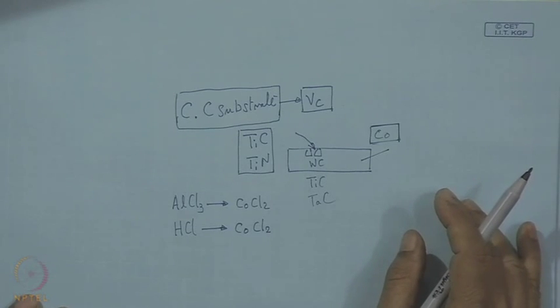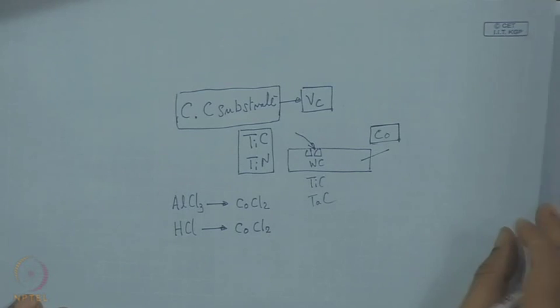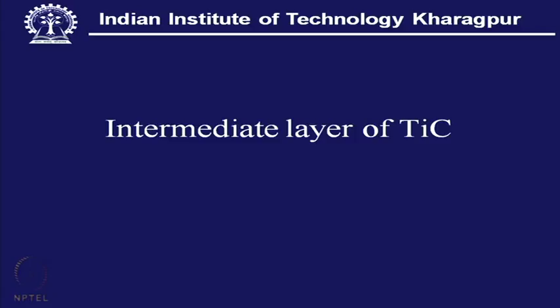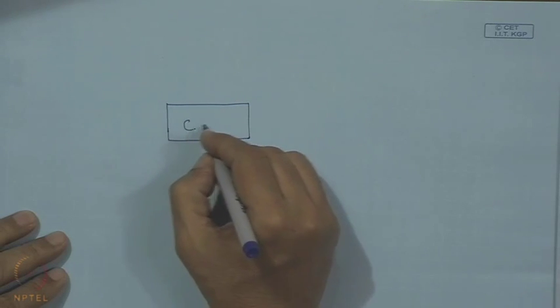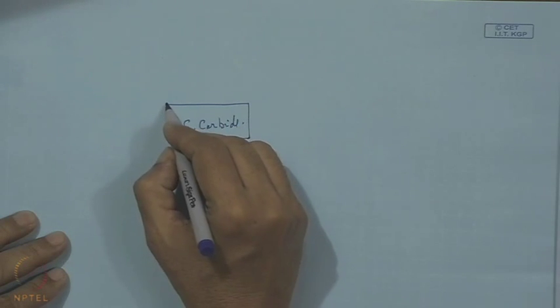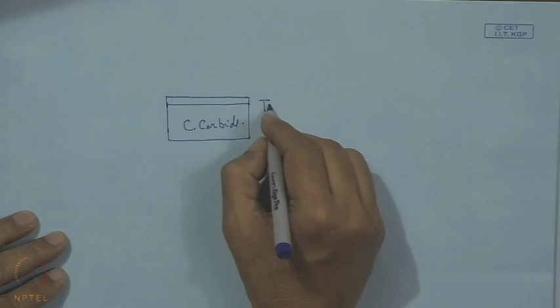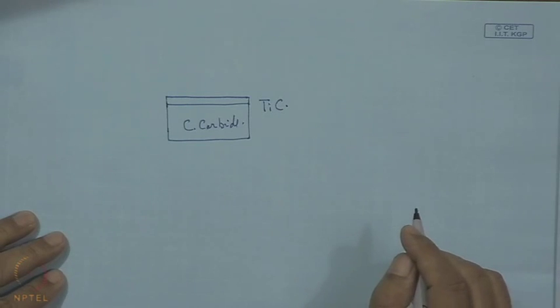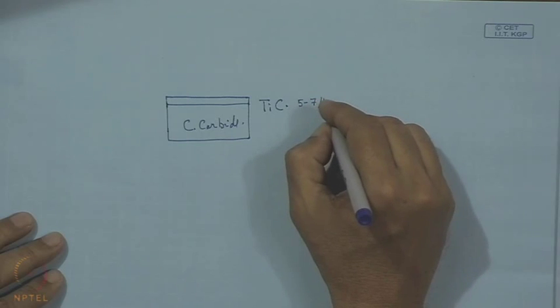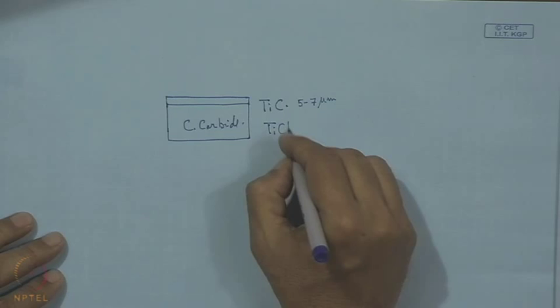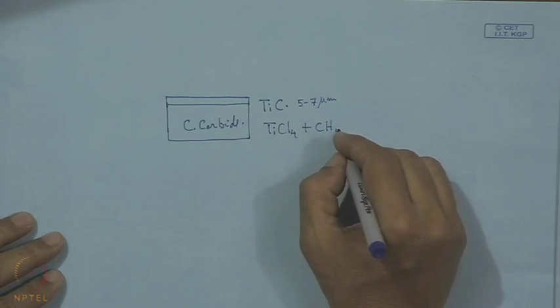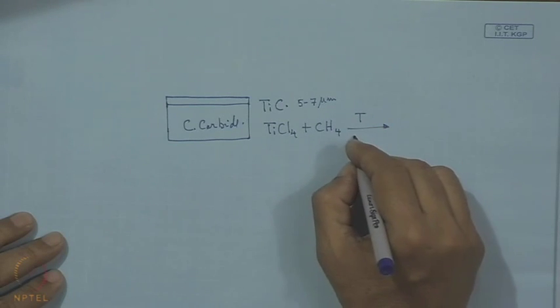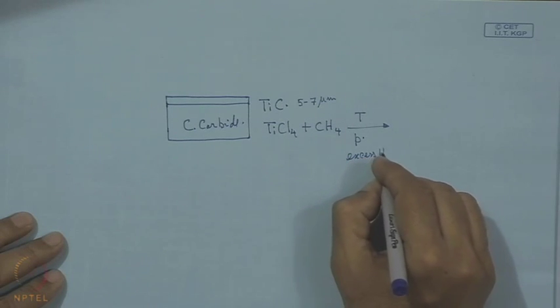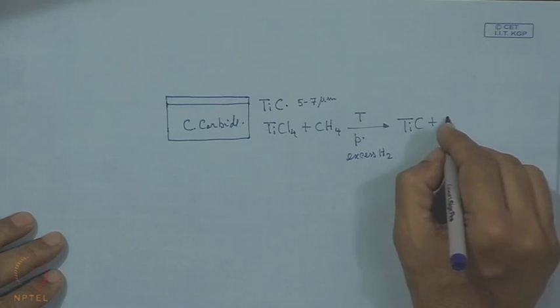So, what is done in this case? An intermediate layer of TiC is put over the surface. So, in this case, this is the cemented carbide, and over that one layer of TiC is grown. It is also CVD TiC, and this thickness is around 5 to 7 micron, and this TiC can be deposited by the reaction of TiCl4 and CH4, with the right temperature, pressure, and excess H2, and that will lead to TiC, and that goes pretty well.